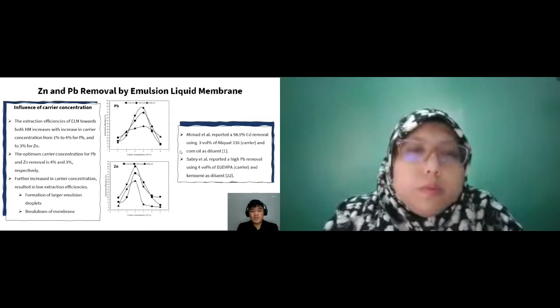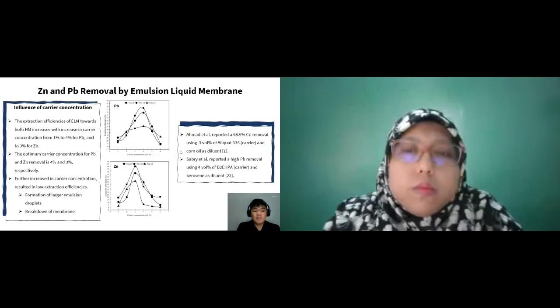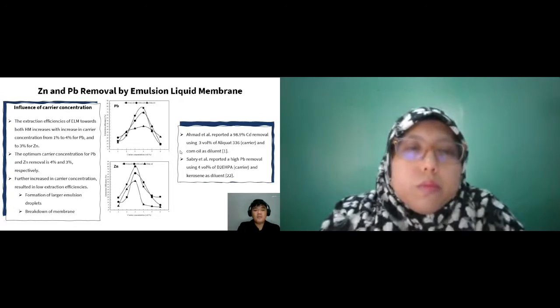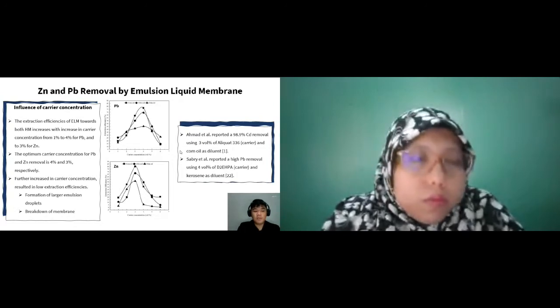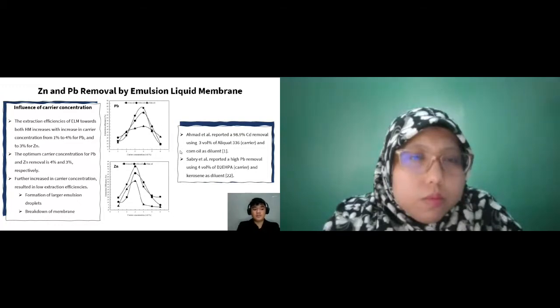For zinc removal, the highest extraction efficiencies were 80.33% using corn oil, 67.33% using olive oil, and 51.83% using palm oil. Optimum carrier concentration for zinc removal was found to be 3 volume% for all types of diluents.